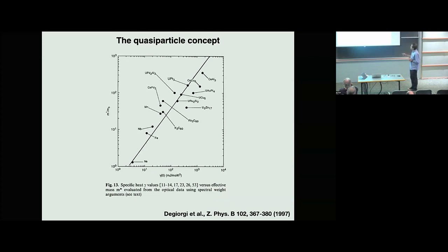So it is a plot of a measure of the mass measured with optics versus the heat capacity on a lot of different material systems, right? You can see sodium down at the bottom, weakly interacting metal, some maybe more interesting things, niobium and iron in the middle, all the way up to heavy fermions at the top. And the point is that there's a linear proportionality between these two different measures of the mass. And I would point out these two different measures are very different experiments, right?